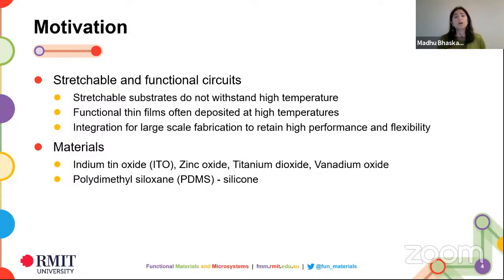For those of you who work on oxide materials, you will know they usually are deposited at high temperatures. They are extremely brittle in nature, whereas the stretchable materials are usually the opposite. They don't withstand high temperatures and they're extremely mechanically pliable and flexible. So what we wanted to do was come up with a technique which allows us to combine two very different materials. We started using silicone rubber or PDMS as the stretchable substrate, and our initial test case was indium tin oxide. Then we diversified into using other oxide materials using the same technique.